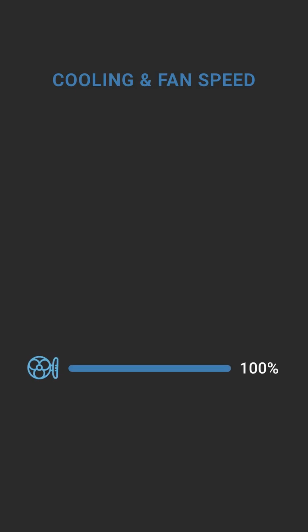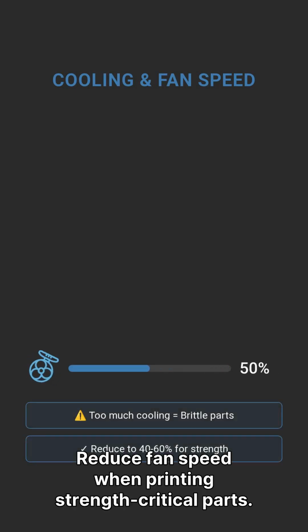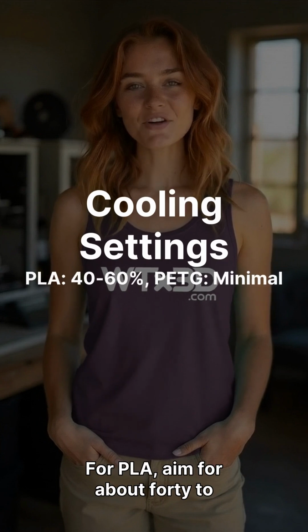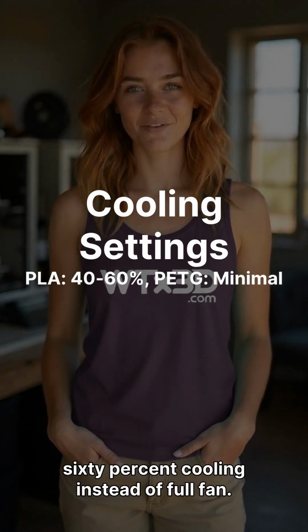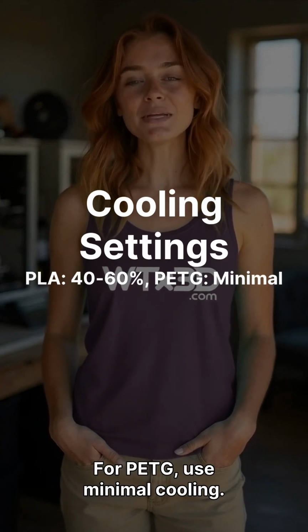Next, cooling. Too much cooling makes parts brittle. Reduce fan speed when printing strength-critical parts. For PLA, aim for about 40 to 60% cooling instead of full fan. For PETG, use minimal cooling.